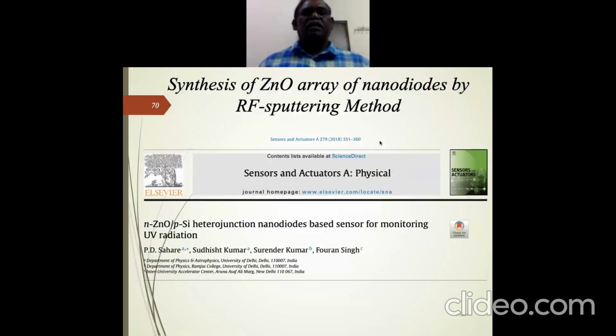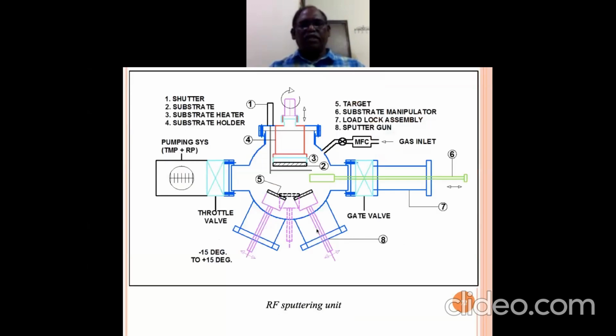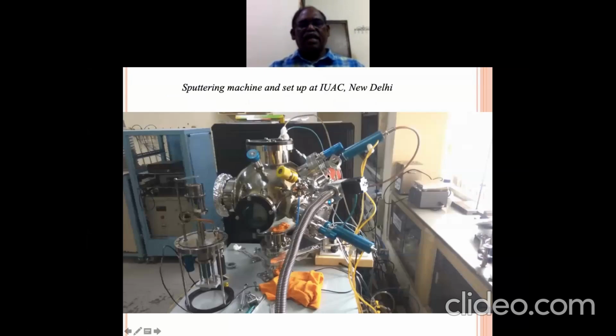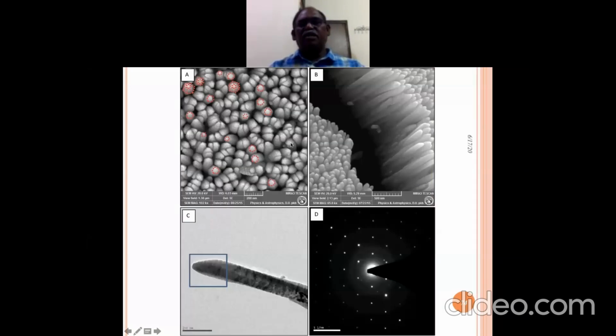So we also have some experience of synthesizing these. ZnO is generally n-type, so we had taken a p-type silicon substrate and grown these nanorods over that, to form a heterojunction nanodiode array. And then this device we have prepared for monitoring UV. So this is the sketch of that RF sputtering unit, and this is the actual machine that we have used. And you can see that very uniform hexagonal nanorods are formed over here.